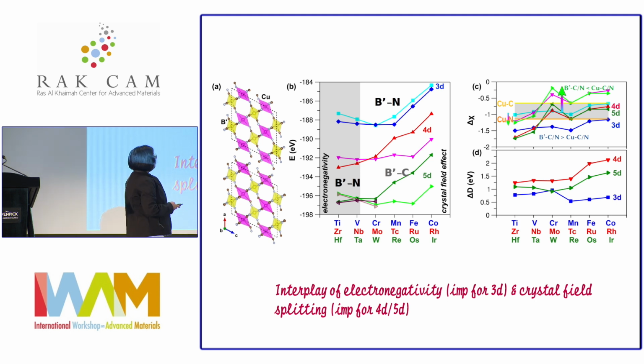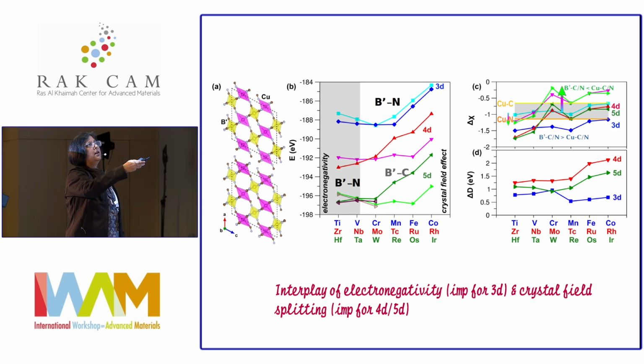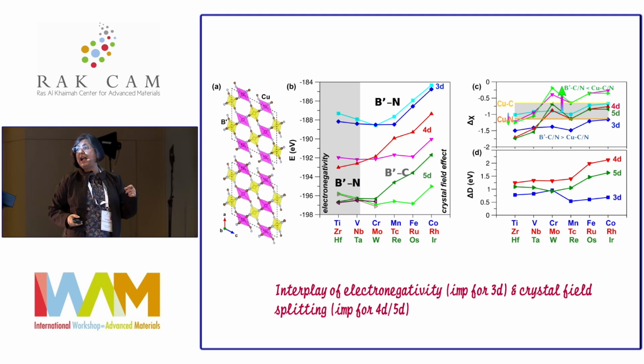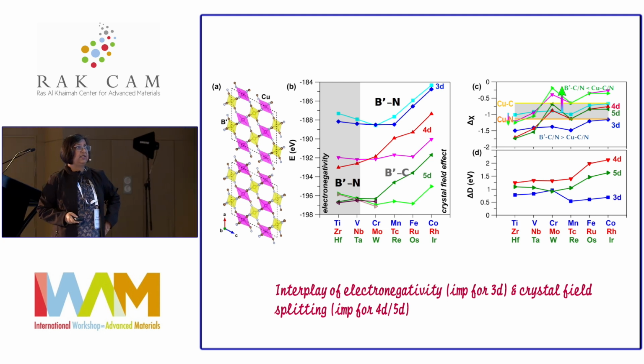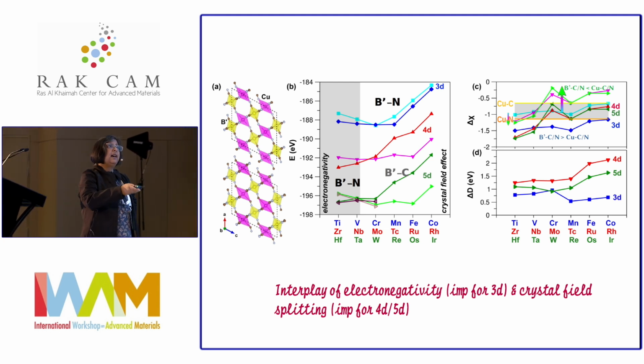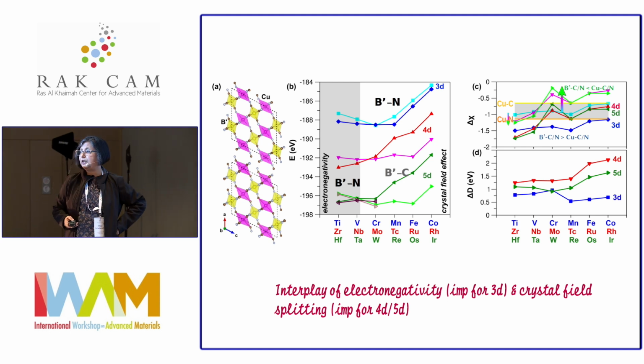While for the 4D or 5D, actually there is a transition that happens as you are moving across the series, from whether it is larger than copper, carbon or copper nitrogen electronegativity to that of the B prime C or N electronegativity. But then it's the crystal field effect that dominates.